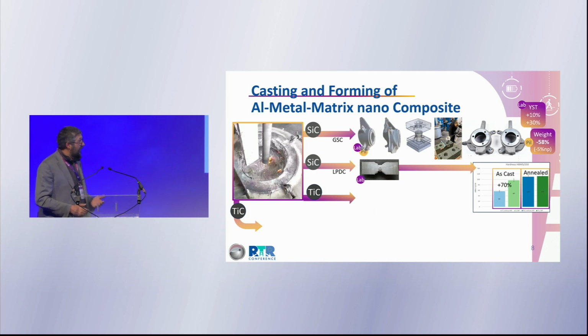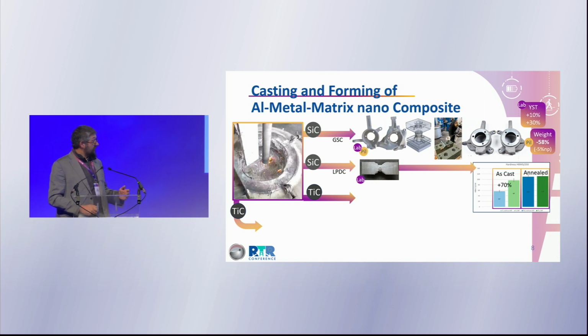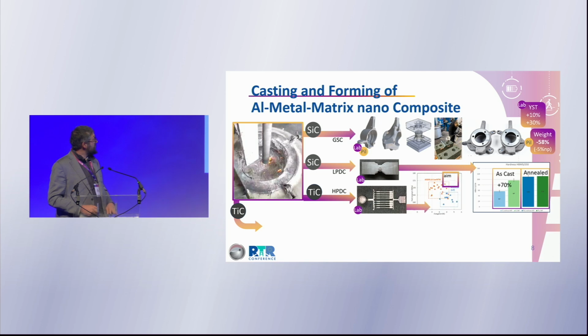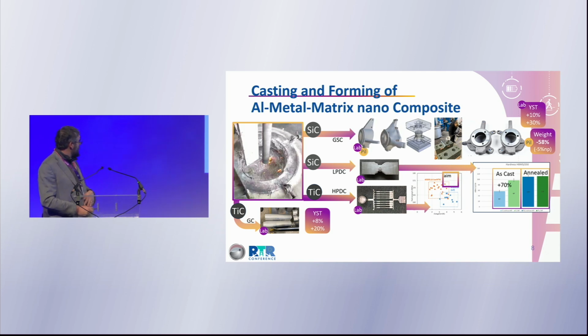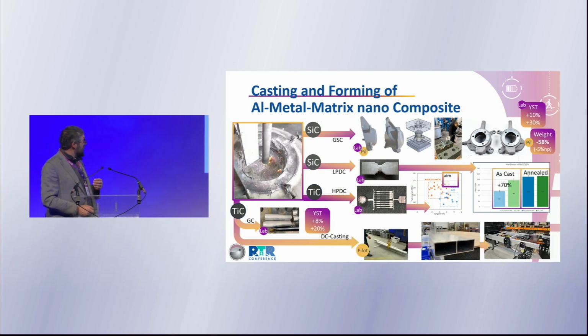So basically, the nanoparticles we were inoculating are competing with the ones that are obtained during the annealing of the components. And we tested titanium carbide on high pressure die casting. We missed the aim area in which we were planning to arrive in terms of properties of yield strength and elongation. And then we got good results in terms of gravity casting, with yield strength increase about 8 and 20%, but we couldn't translate properly that into the die casting.